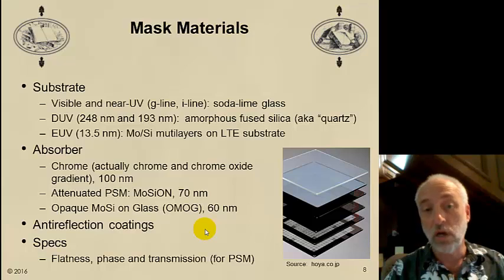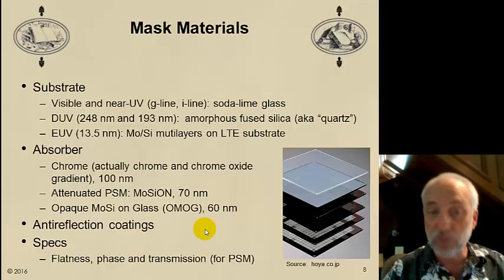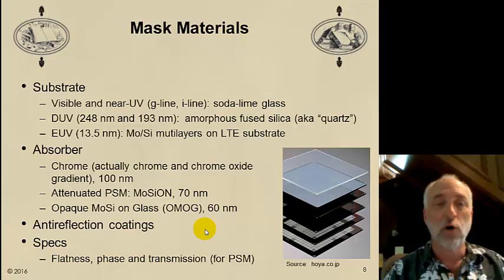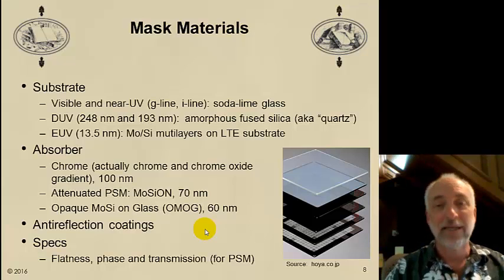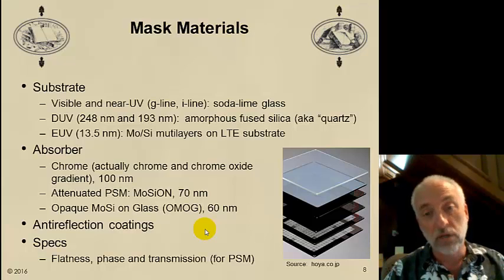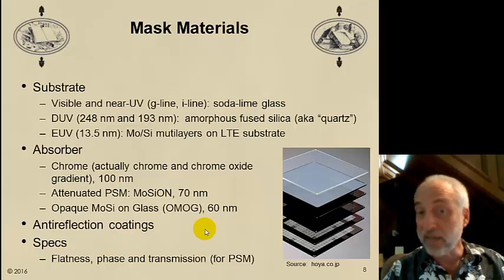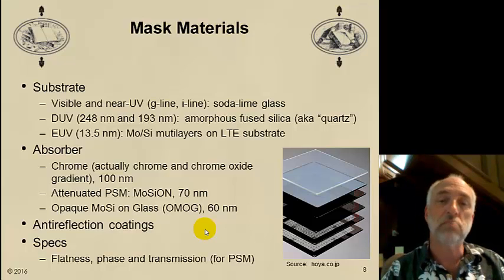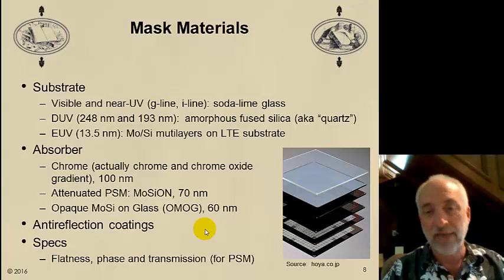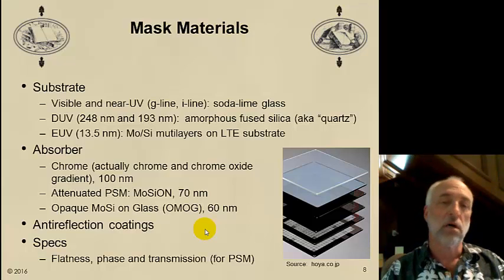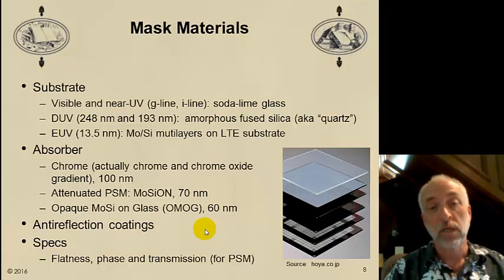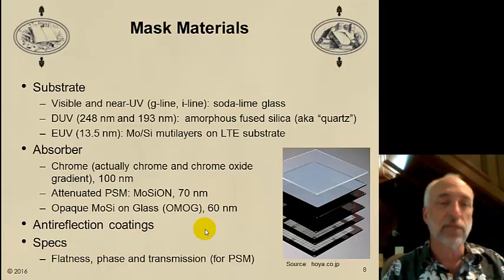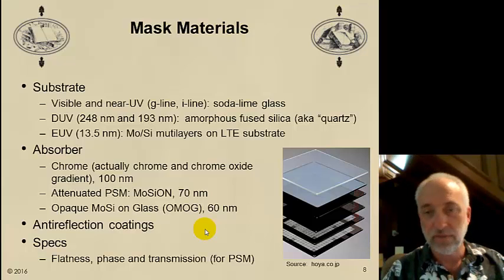We also use opaque MoSi. MoSi is molybdenum silicide. Opaque MoSi on glass, or OMOG, is another popular material that replaces chrome. It's opaque like chrome is, but it's a little bit thinner. We can get down to 60 nanometers, and it results in better optical performance to have this thinner rather than thicker material to do our diffracting. We also have some anti-reflective coatings on both sides of the glass and on the chrome itself to minimize reflections. We won't go into any of the details of this.